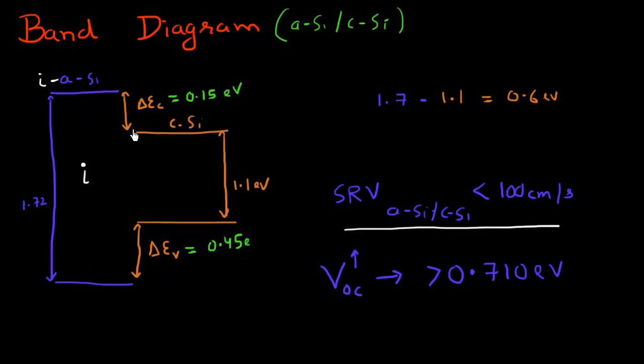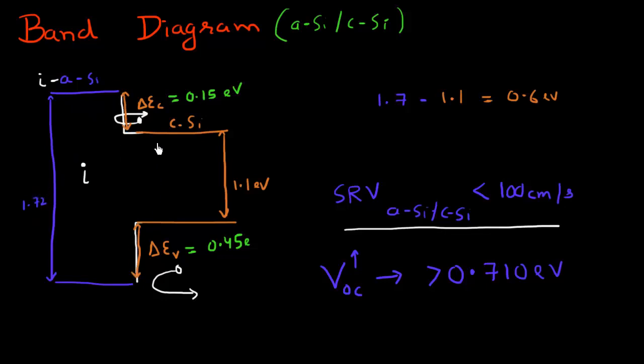That presents a challenge because you have this high conduction band and valence band offset. You could utilize one of these offsets. For example, if you want to make a good hole barrier layer, this offset would essentially prevent your holes from coming through. But you also have this conduction band offset, so it will also repel the electrons which are trying to get collected at this side as well. The presence of both these offsets blocks the holes but also blocks the electrons.